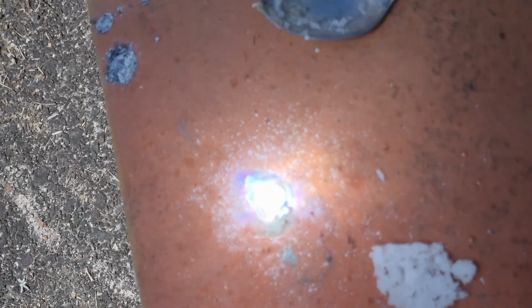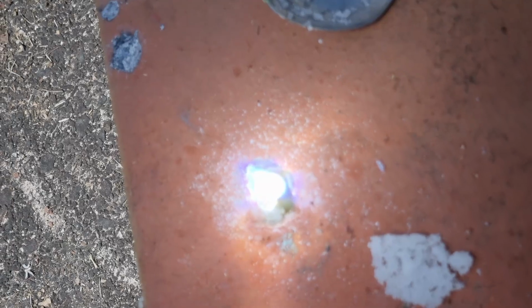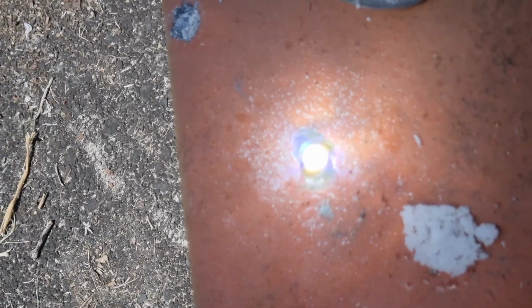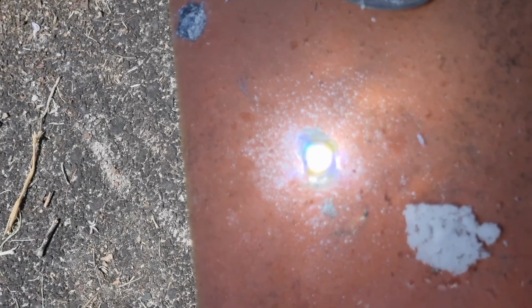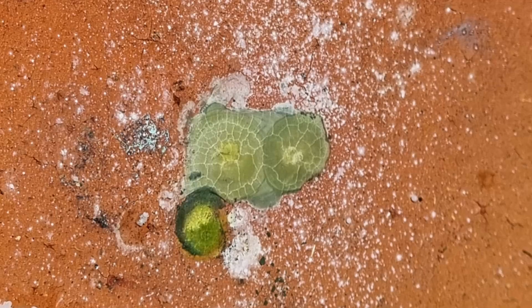Now you might ask, would this method work starting with alternative sodium sources such as sodium hydroxide or even sodium chloride? The answer we found was actually probably yes. Doing the same with sodium hydroxide does produce some yellow product, but because sodium hydroxide melts at a much lower temperature, the reaction is much messier.